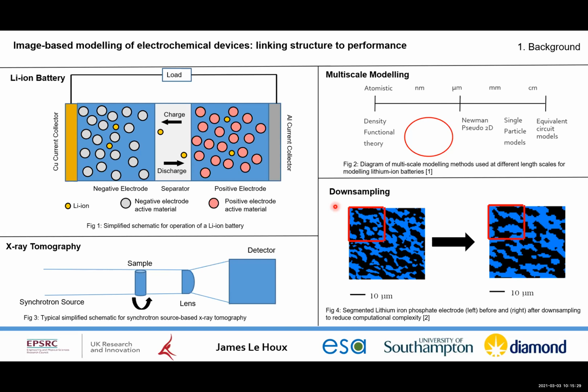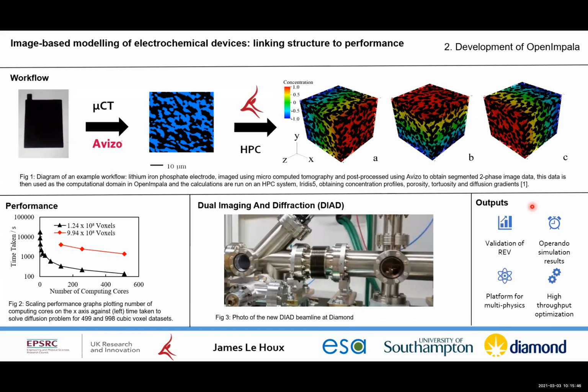So typically we use a process known as downsampling, where we reduce the resolution used, which then reduces the computational cost associated with it, but maybe gets us a bit further away from the reality. We can see we're closing off some of the pores in this case on the bottom right. So what my PhD was looking at, and this is my PhD in a slide, is to develop these image-based modeling techniques, but to deal with these larger data sets.